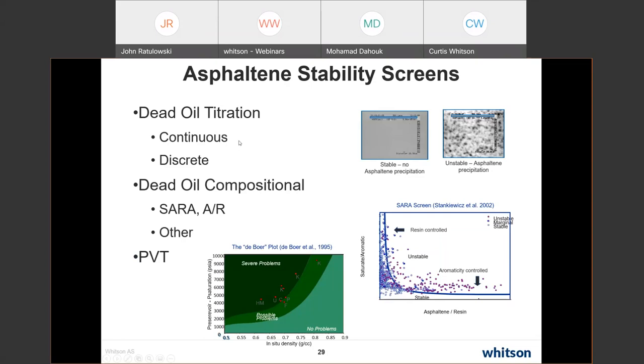You can either do it in a continuous titration where you continuously add the precipitant at some rate, or you could do it discrete where you put the precipitant in, you shake it up, and you give it time to equilibrate, which again was the way we did it at Shell, where we would actually let it sit for quite some time to try to take out the kinetic effect in this measurement. So you can see here visually, stable, no asphaltene present, unstable, asphaltene has come out of solution. Sometimes it's really hard to see, like in the wax, if you have very small amounts of asphaltene coming out.